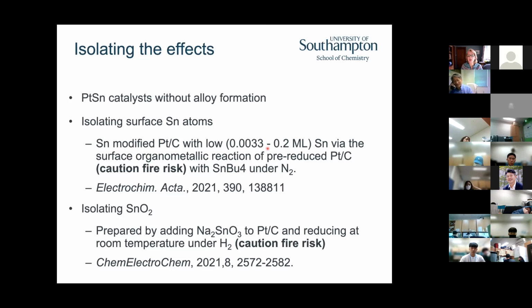We're going to deposit this by reducing the platinum in hydrogen, and then adding this species, the butyl tin, under nitrogen. If you want to reproduce these results, please be very careful that you have completely removed the hydrogen gas before you add the butyl tin, and do it all under nitrogen, or it will catch fire. We can similarly take our parent platinum on carbon and add tin stannate. If we reduce that at room temperature in hydrogen, we can just leave the tin oxide decorating the platinum particles without forming the alloy.